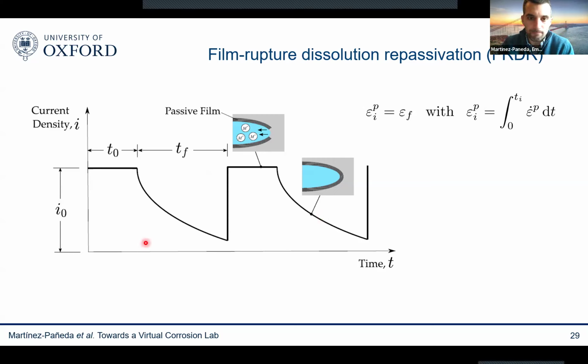So we know that, as you passivate a layer into the metal, you are lowering your corrosion current density. But then eventually, when your strains are large enough, then you rupture the layer, and then you enhance corrosion kinetics. And then after some time, you start generating and repassivating the layer again. So basically, it's a cyclic process, a competition between repassivation kinetics and mechanical straining kinetics.